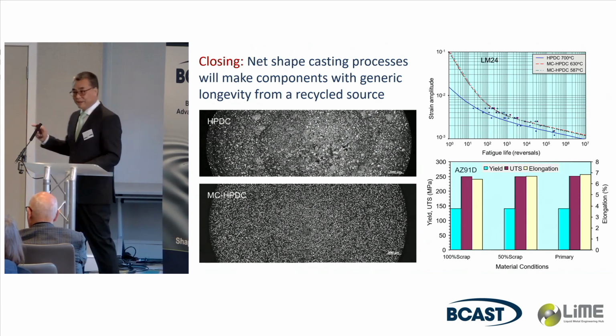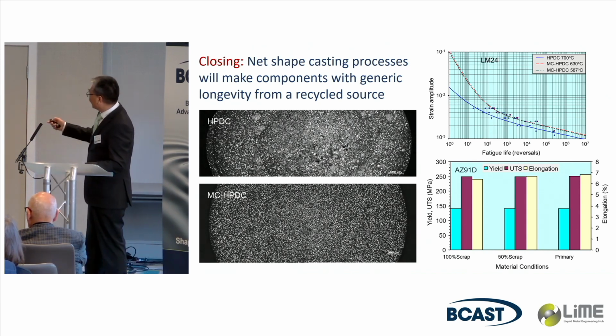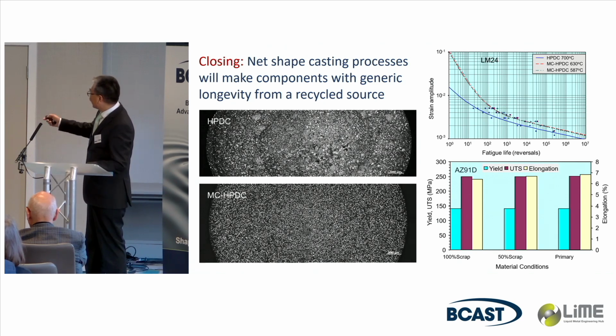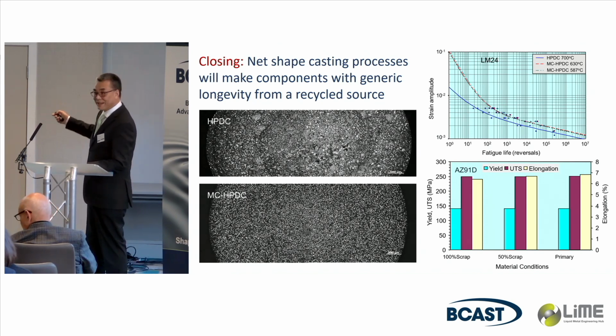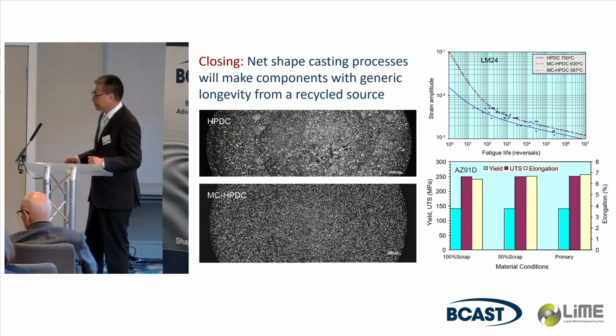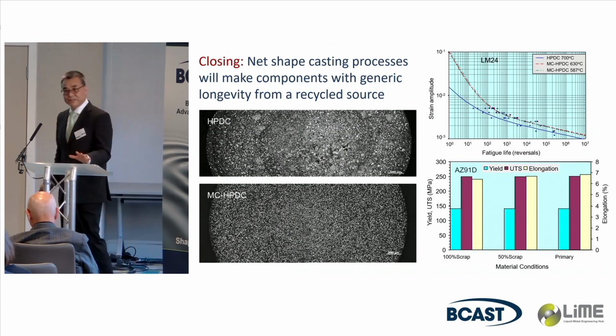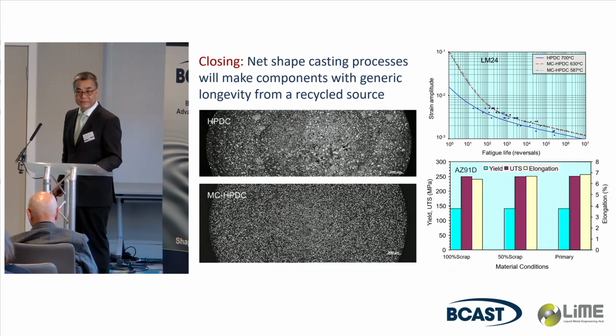By doing that, what you get is very, very interesting here. This we worked on with Zhongyun over 10 years ago. They tested the mechanical performance with this and this. The blue line here is conventional, and the red line is with MC, what we call mild condition. You can see that's an order of magnitude longer life with the same strength, okay?